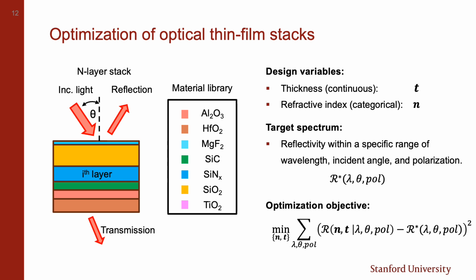Design methods based on physical intuition result in limited performance, and they are generally difficult to scale to aperiodic thin film stacks comprising many layers. To address this limitation, various global optimization approaches have been explored, including particle swarm, needle optimization, and the genetic algorithm. These methods are all derivative-free global optimization methods. They search the design space through the evaluation of a batch of samples without any gradient calculations, which actually limits their ability to reliably solve for the global optima.